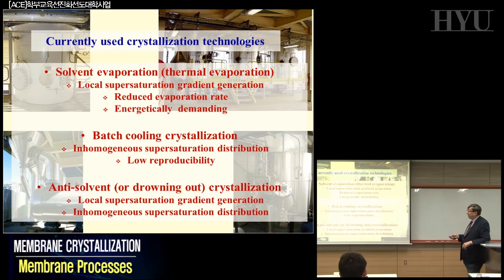Another way of doing is batch cooling crystallization. Instead of warming up, you can also cool down. That's another way of doing, and you have the same result. Normally, when you are working in batch cooling crystallization, it's not easy to reproduce the performance of the system. You very easily have inhomogeneous supersaturation distribution. What we have mentioned before is very important, and here it's very difficult to keep control. So if you want to have high quality crystal with what we call low variance, a very small size distribution of the size of the crystal, etc., batch cooling is not the best way of doing.